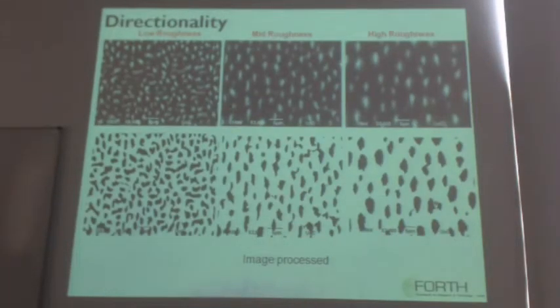And as I told you, this comes solely from geometrical means. Here is a top view of the different types of surfaces used: the low roughness, the mid roughness, and the high roughness. And here are binary images, image processed, so pixels give us 0, 1 images. You can see here that while in the low roughness there is a spontaneous orientation of these posts, there is an elongation of these posts in the mid and high roughness case.